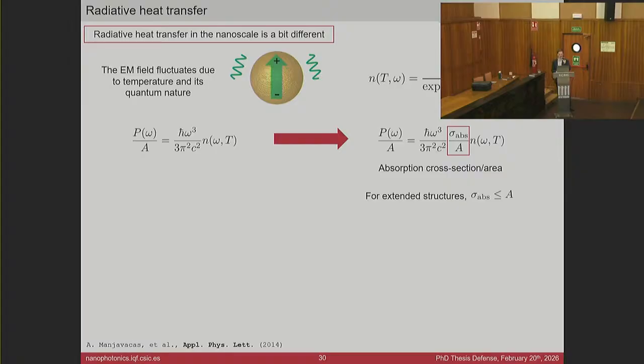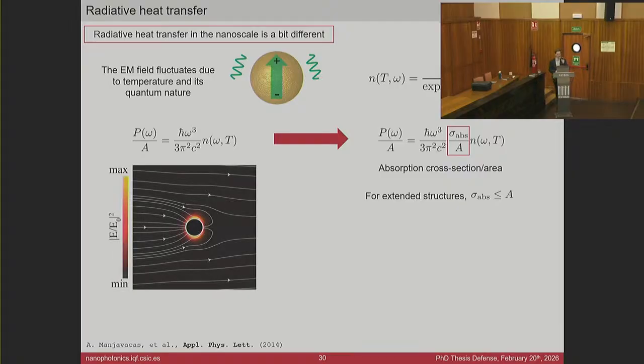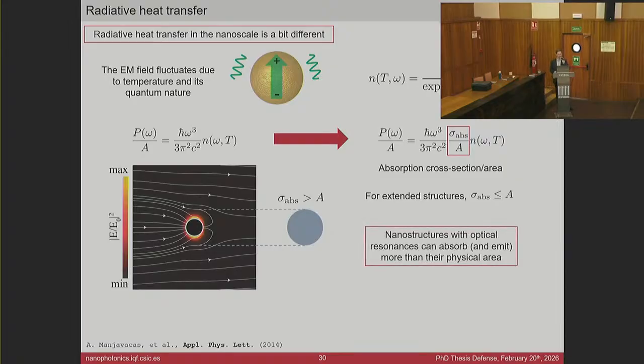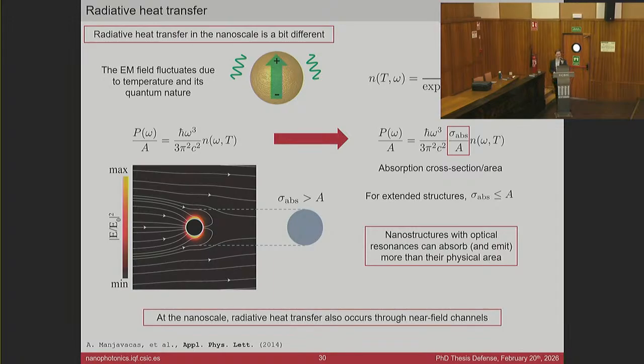And while for extended structures, this ratio will be less than 1, giving rise to gray bodies or black bodies in the best case, for nanostructures, we can have absorption cross-sections that are larger than the geometrical area. And in such a way, we can have nanostructures that will emit or absorb more than what they were supposed to do according to the geometrical area. Not only that, but in the nanoscale, if objects are in close proximity, we can also make use of the evanescent fields to further increase this transfer of energy.